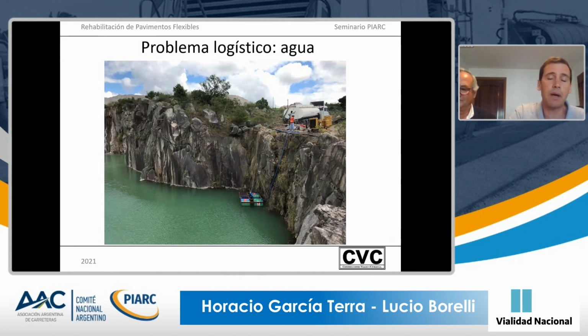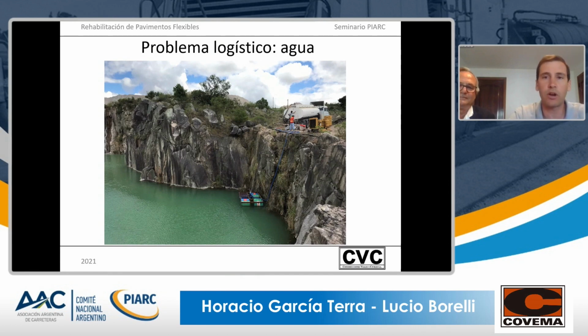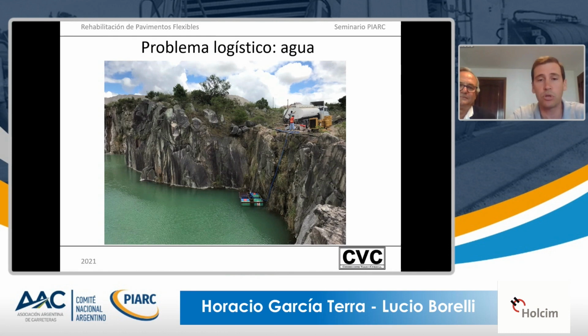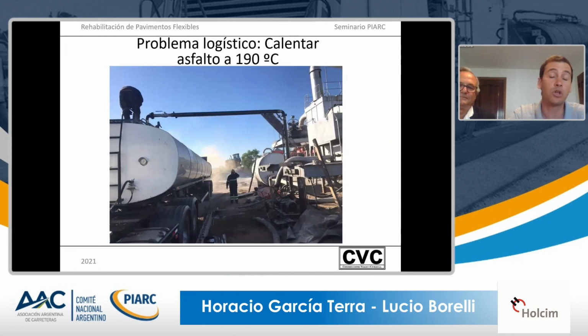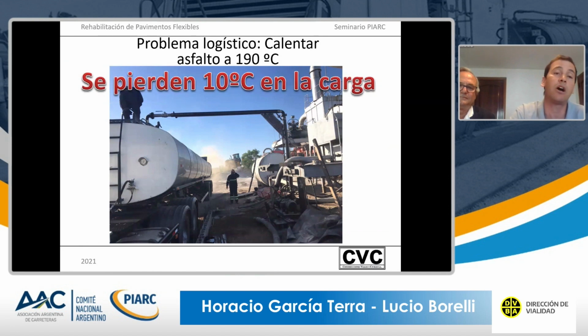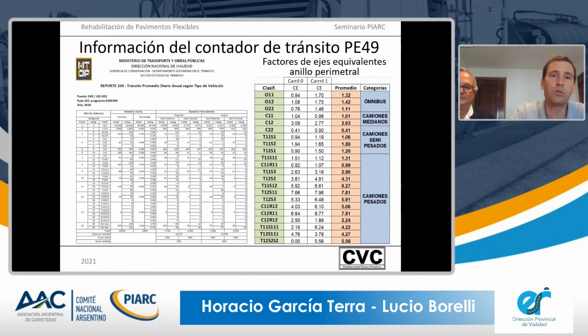A very important logistic problem that is not taken into account many times is the consumption of water. A lot of water is consumed in compacting and in keeping the stretch wet, and it really is an issue in many regions or places to get that amount of water. Also, the warming of the asphalt at 190 degrees centigrade when we need it at 180 degrees. So in order to have the tank or the mixer working at 180 degrees, we lose 10 degrees centigrade.